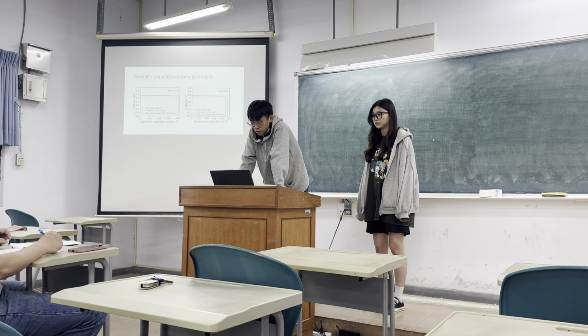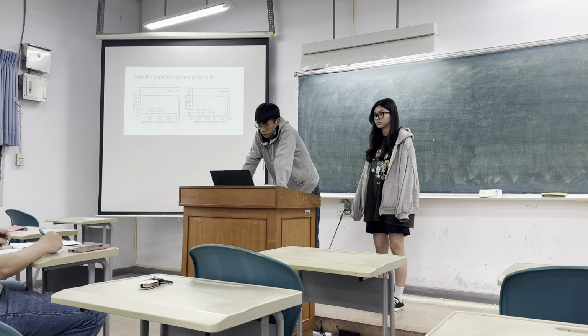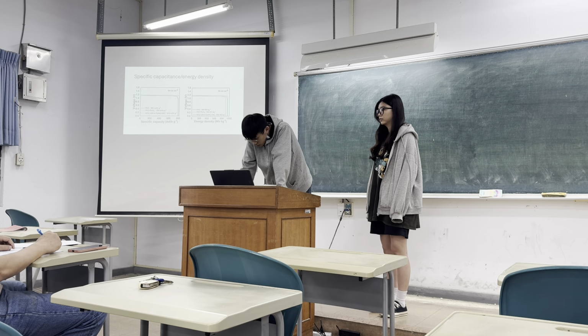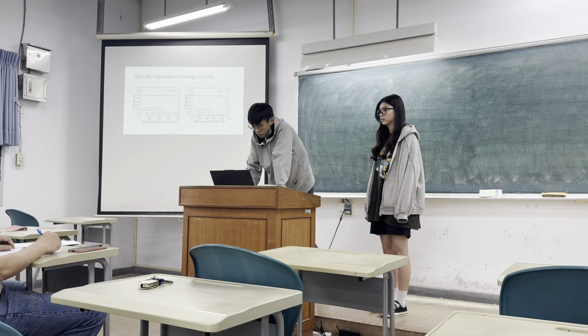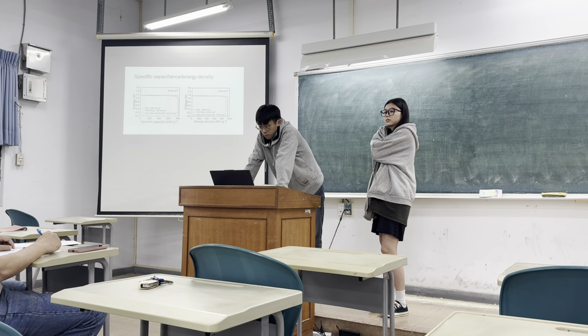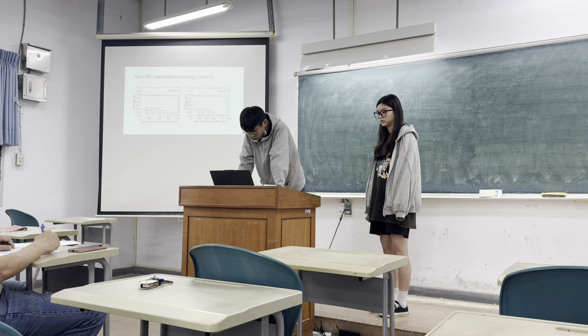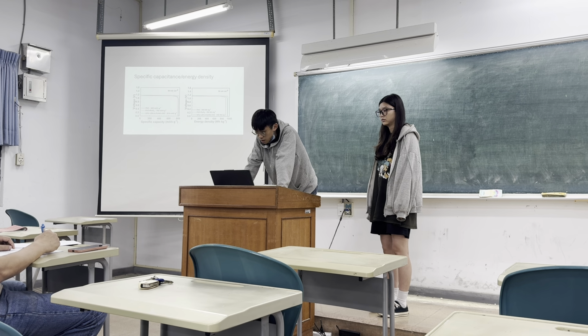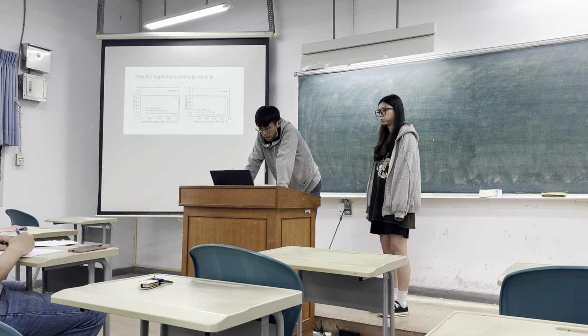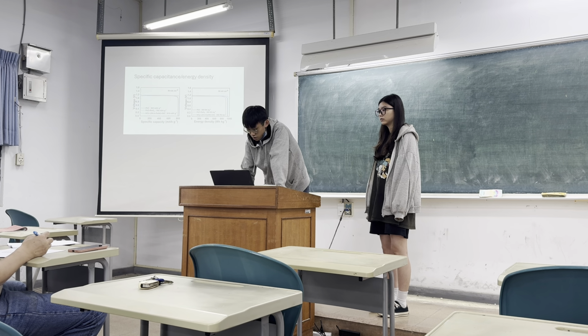Specific capacity means how much charge can be delivered per gram of zinc. With the unit of milliamp hour per gram, a higher value means better utilization. In the figure, LDH efficiency shows a stable discharge voltage of about 1.15 to 1.16, and the voltage drops rapidly after reaching 818. This value is higher than PTC 803 and PTC plus RuO2 at 792, showing better discharge stability.